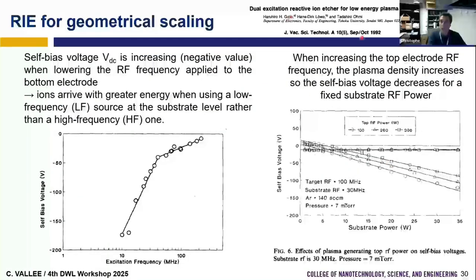And you can see again with this paper that depending on the frequency, so as I said, if you increase the frequency of the generator at the bottom, for example, you will develop less self bias because you will develop less peak to peak. So it means that the DC self bias is low. And we say that the ion energy is Vp minus the DC self bias. So the ion energy will be low. But if we use a low frequency generator at the bottom, now we develop more DC self bias. So we have higher energy. So it is better to use a low frequency generator to have highly energetic ions coming to the substrate.